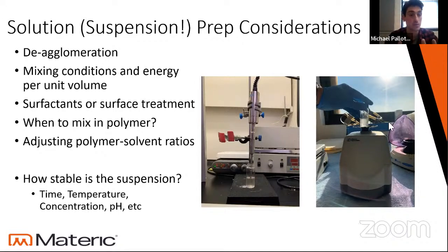and finding out that the uniformity wasn't quite there. So we needed to do 2 separate steps and then mix them 15 minutes later to find that the uniformity within the nanofiber mat that we created fit the description for our customer down the line. And then adjusting the polymer solvent ratios.